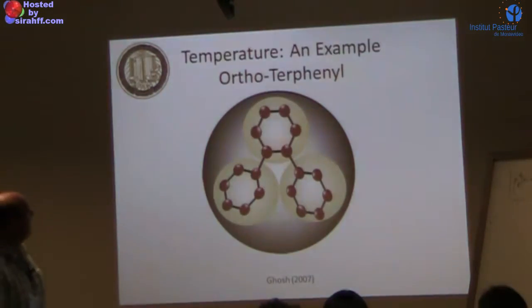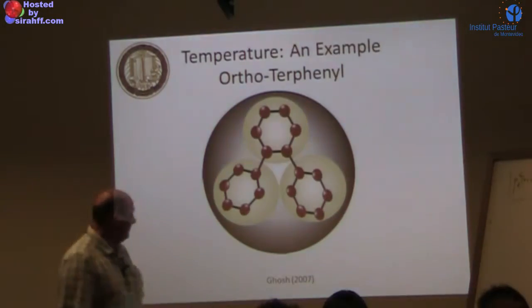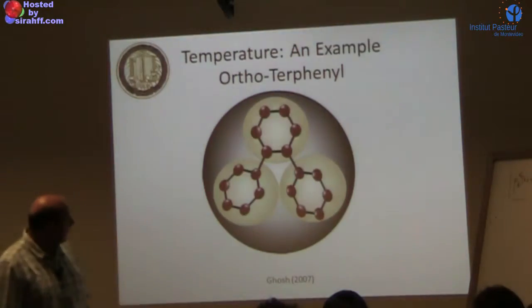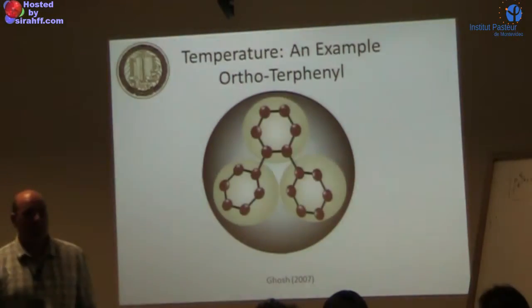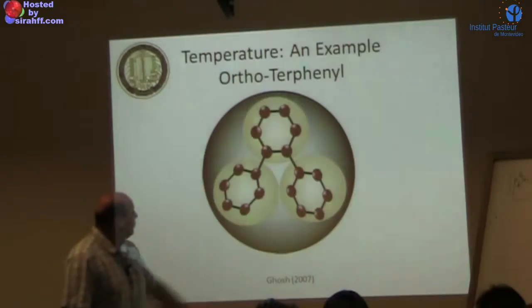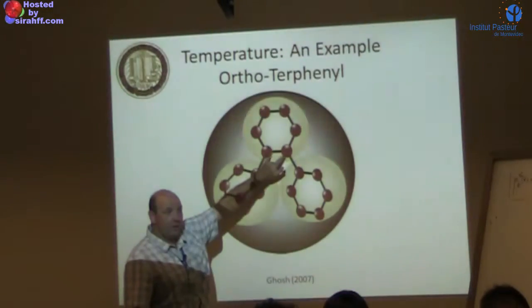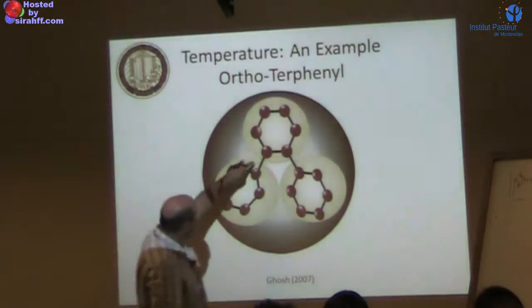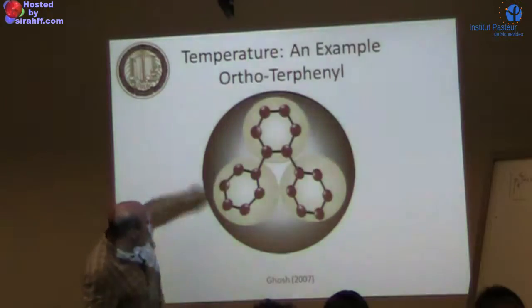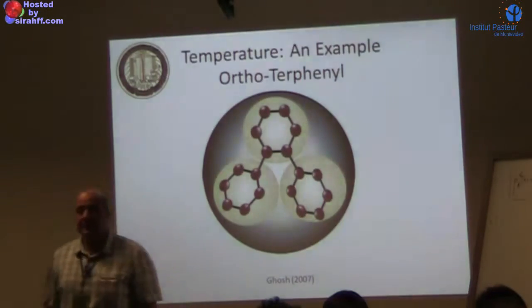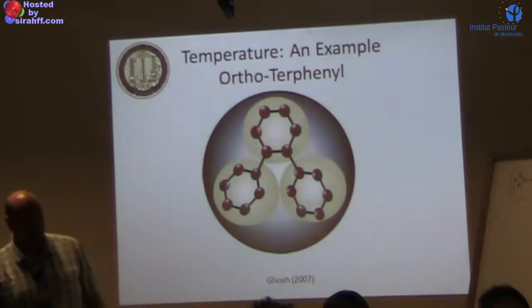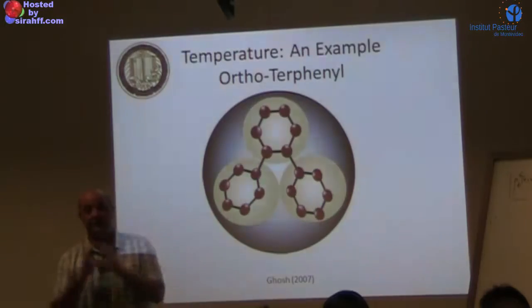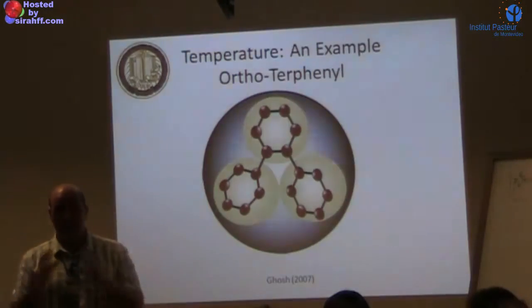This work on OTP was done by Ghosh five years ago. OTP is a very simple molecule — you take three phenyl rings and connect two in ortho-position on the middle one. The mapping is onto three interaction sites: the central ring and the two outer rings. The two outer rings must behave the same because they are symmetrical, while the central ring may behave differently.